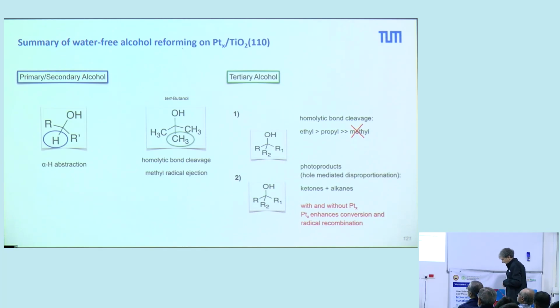So we can apply, I hope I could show you, that we have a new mechanism. If you use primary and secondary alcohols, we have an alpha H abstraction. If we have a butanol, we have this radical ejection, and if we have general tertiary alcohols, we have a selectivity. We split these hydrocarbon chains, and probably the selectivity is steered by the stability of these radicals, ethyl or propyl radicals. And so we can also tune the selectivity here.